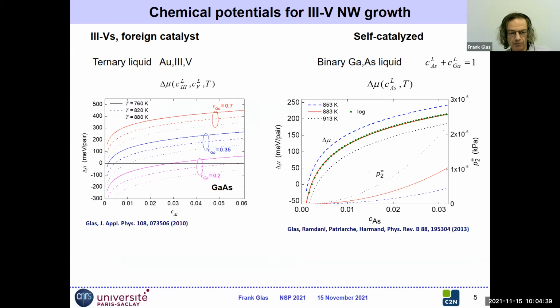Now, chemical potential is important. So here are two calculations of the difference of chemical potential for a 3-5 pair between a liquid and a solid. On the left, you have the case of gold-catalyzed nanowires. On the right, the case of self-catalyzed nanowires, where we have no gold. The liquid is a binary gallium-arsenic liquid. And in both cases, this is as a function of the concentration of arsenic in the liquid. And you see that very small concentrations of arsenic, a few percent, are enough to ensure large values of this difference of chemical potentials. And actually, we are sure that the concentration of group 5, or arsenic in the case of gallium arsenide, is very low in the liquid. We don't need more.